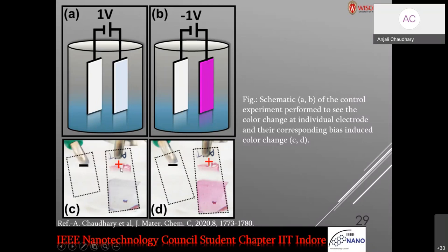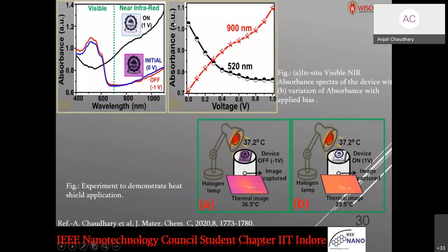We used tungsten and thiophene, and we see that there is a color change when you apply a positive bias to the thiophene based electrode and negative to the tungsten electrode. They are transparent at 1 volt and -1 volt. The thiophene goes to its initial magenta color and nothing happens to the tungsten. Tungsten just helps in improving the IR absorbing part, as we see in this spectra.